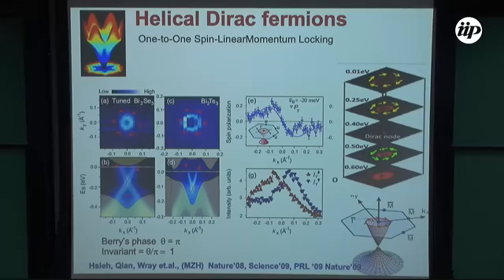So then what we do, we not only image these surfaces, we also image the bulk, and we also image these states by scanning the chemical potential across the gap. What we see is that no matter where you place the chemical potential in the gap, you always have these surface states. And their spin texture is reversed as you go through the Dirac node. So this guarantees that you always have an odd number of crossings as you count from the center of the zone to the boundary. So then you have a single crossing.